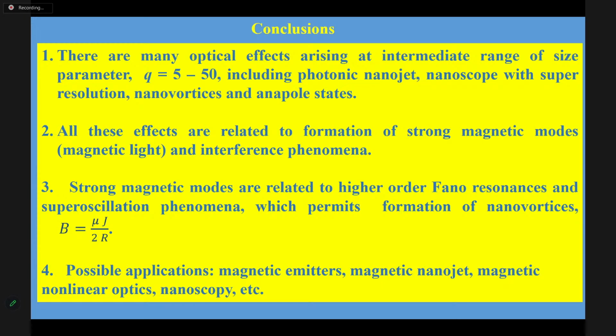Very interesting result. And so, how big a magnetic field has been produced? What is the duration? What is the scale? We used a ratio of the magnetic field really measured compared to the magnetic field in a plane wave. So we illuminate the spherical particle by a plane wave, and take the ratio of the focused magnetic field to the magnetic field in the plane wave. Experimentally, we show that it can be, for the first resonances, even 1 million times.